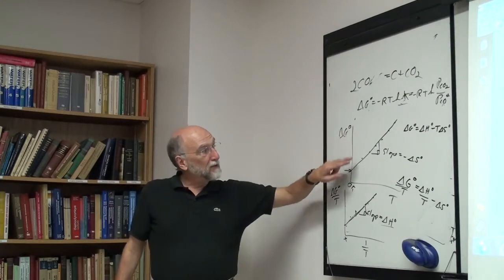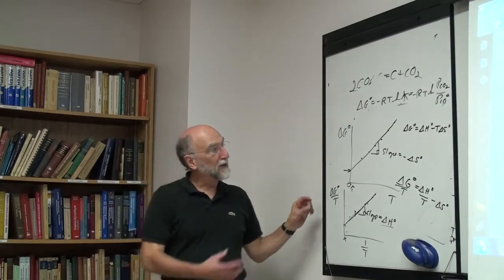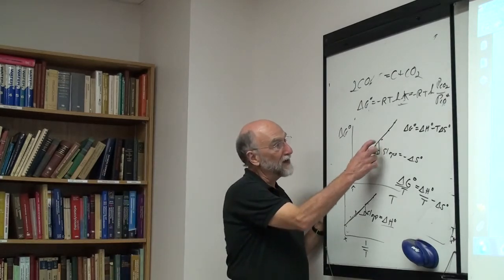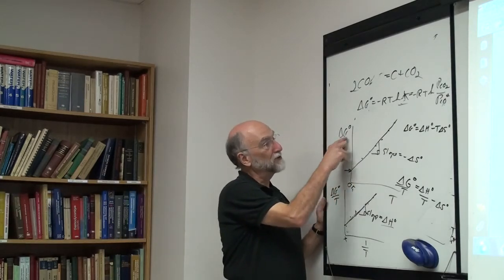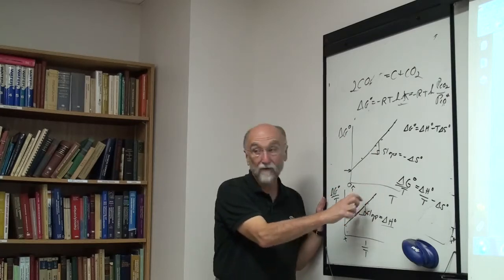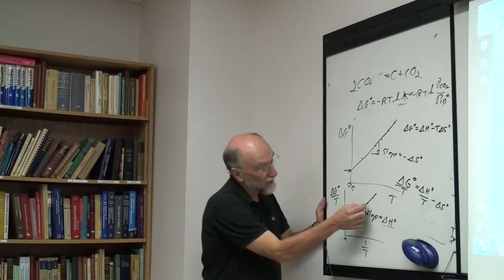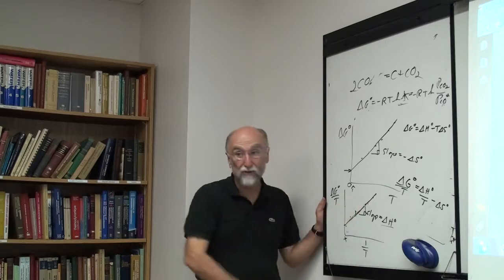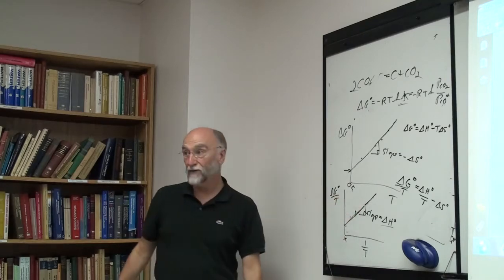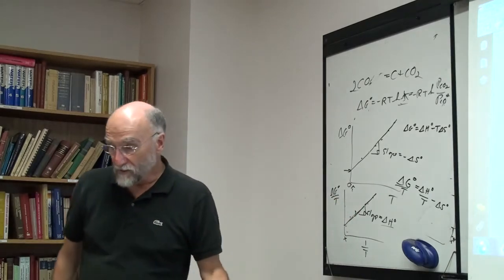The delta G can be measured very, very accurately, but you've got to be careful. The delta G can be very accurate, but if the temperature range is small, the delta H and delta S can be very inaccurate. A very slight difference here and a slight difference here can change the slope tremendously if the temperature difference is very small. So there's a danger in that.